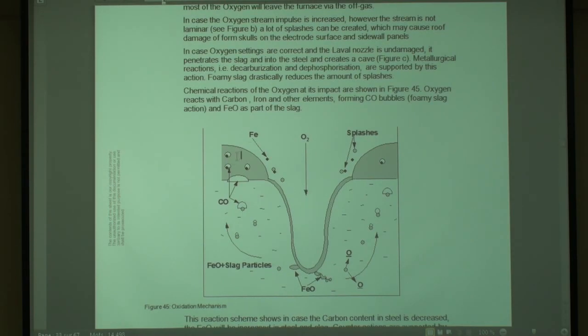When you inject carbon in the slag, you see these particles of carbon here, and they meet the FeO of the slag, and then it creates a small CO bubble around. Yeah? And of course then the lifetime of the bubble in the slag makes the thickness of the foam. Okay? If you have fine coal, you create more bubbles, so it's easier to foam. If you have bigger grain size, you have fewer bubbles, so the foaminess is not so easy.